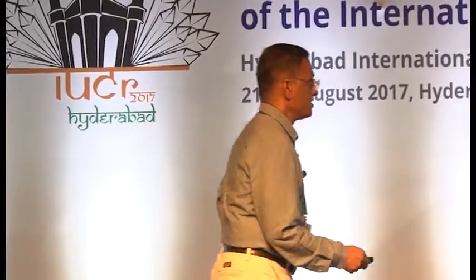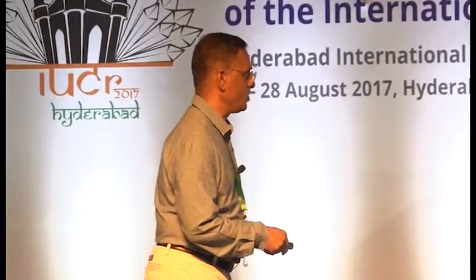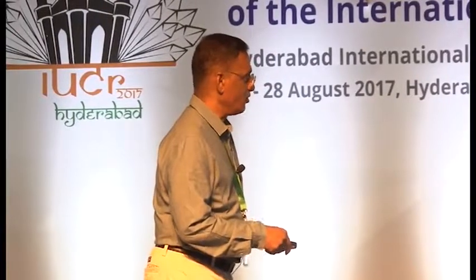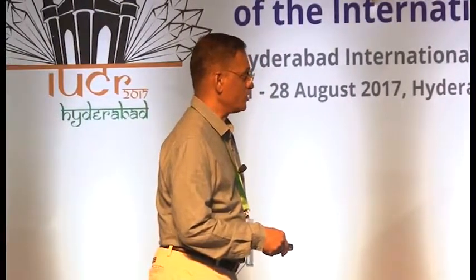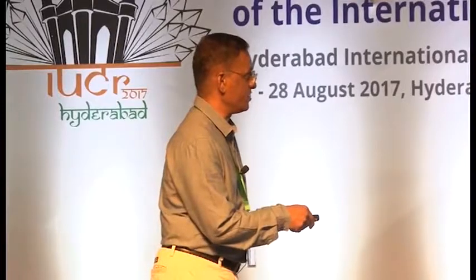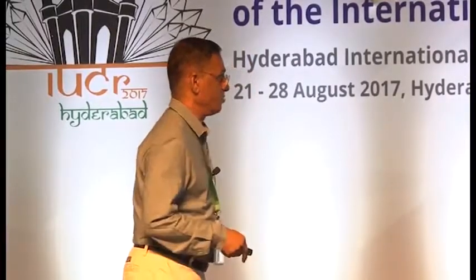Here, this slide shows what happens if you change the substitution. Even for the same 3F, I've shown that if you try to crystallize from DMF water, you start getting the curved crystals. If you change the solvent to methanol, you get a normal crystal, photoreactive crystals that undergo 2+2 cycloaddition reaction due to the presence of the olefin bonds here. When you change to 2F, then that shows photosalient behavior.